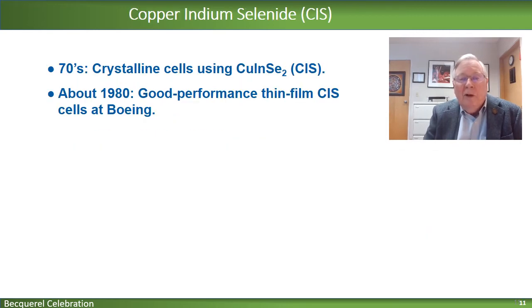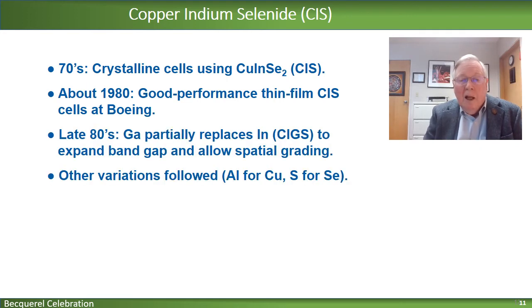The copper indium selenide, which initially at least was CIS, started as crystalline cells in the 1970s. And around 1980, good performance thin film CIS cells were being made at the Boeing company, which did a few things besides airplanes. In the late 80s, it was discovered that if you partially replaced the indium with gallium, you could expand the band gap, and you could also allow spatial grading of a band gap. And so that's why we usually hear about CIGS. And other variations followed with aluminum for copper, sulfur for selenium, and so on.